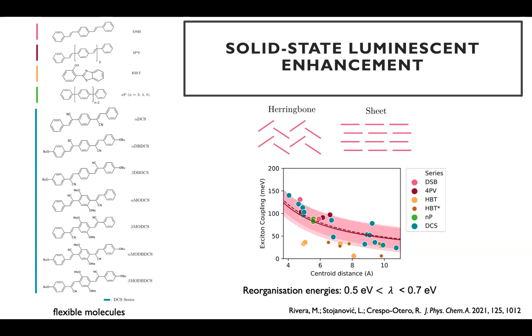Essentially, the transport is going to go through incoherent hopping, essentially because the excitations are clearly localized on a single molecule or on a few molecules in the system. So a good way of checking that, and that happens for most molecular crystals, is looking at the values of reorganization energies, just to have an idea of how much the relaxation that happens in the system in the excited state can compete with the values of the exciton hoppings, which will give you an idea of how important the transport will be in comparison with the localization of the excitation.